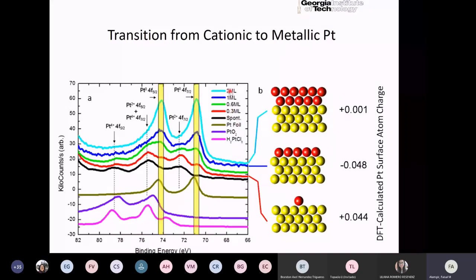What we notice is that in addition to metallic platinum, which would be given by this band of yellow, we also have these other peaks that represent cationic platinum. That means we have, in addition to metallic platinum, also ionic platinum, and only after you go past one monolayer of platinum do you start to have the metallic nature of platinum evidenced.